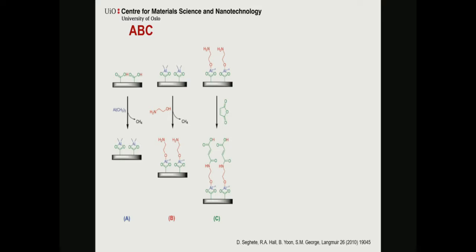It's not always like that. You can get nice reactions to the diamine and the trimethyl aluminium as well, but you have a huge difficulty in characterizing the film later on because it's going to react instantaneously when you take it off the reactor. Whereas the one with the alcohol is going to also react, but not instantaneously. So we have tried that as well.